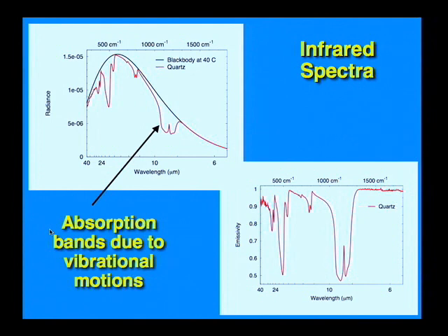If I just measure the straight radiance, then those curves are moving up and down with temperature. The shape of those curves is changing slightly. But the ratio of the energy emitted from a natural surface to an ideal surface stays the same. So this emissivity doesn't change whether I'm measuring it at 20 below zero or at 500 degrees centigrade. This emissivity of quartz won't change.